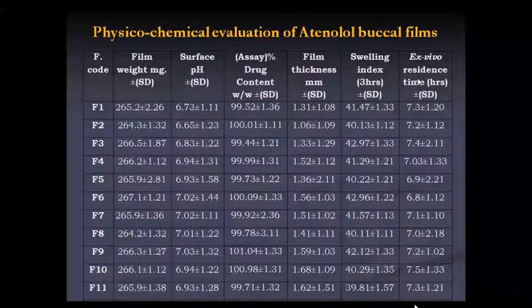Surface pH. When we apply the film on the buccal cavity, there is a possibility of irritation, because of changes in the pH of the film when compared with the buccal pH. So it is mandatory to check the surface pH of the film, which must be nearing 7, neutral. The salivary pH is also in the range 6.2 to 7.1. So if the film surface pH is within that range, it won't cause any irritation or any allergic reaction towards the film.